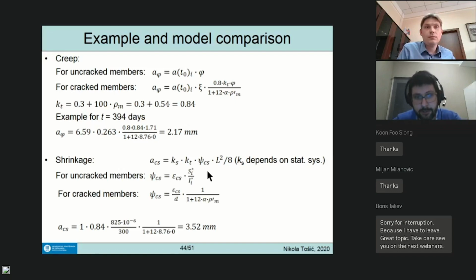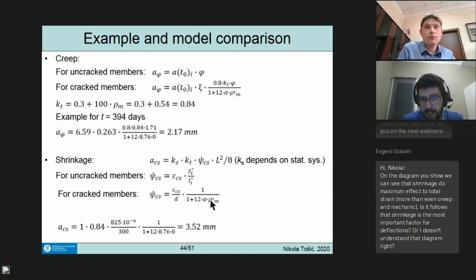CS is the curvature from shrinkage. If it's uncracked, it's like this; if it's cracked, it's the shrinkage strain over effective depth, then 1 over 1 plus 12 alpha rho m. When you multiply everything, Ks, KT, strain over depth, and this part, which for us is 0, we get 3.52 millimeters.